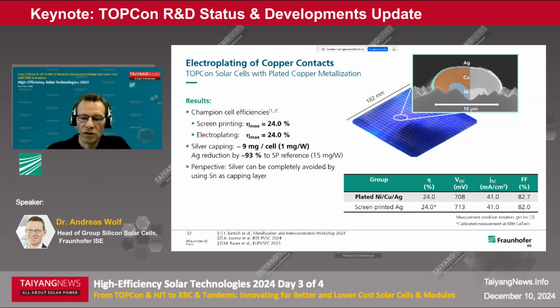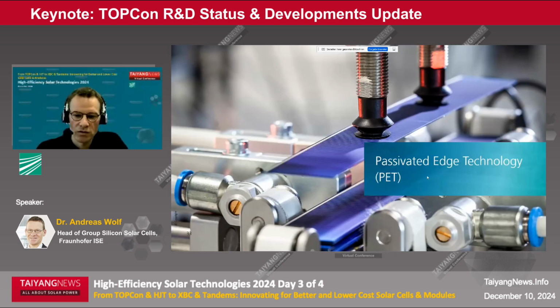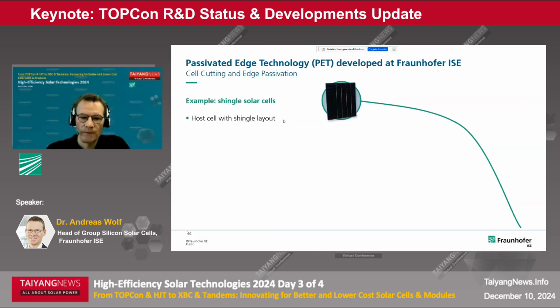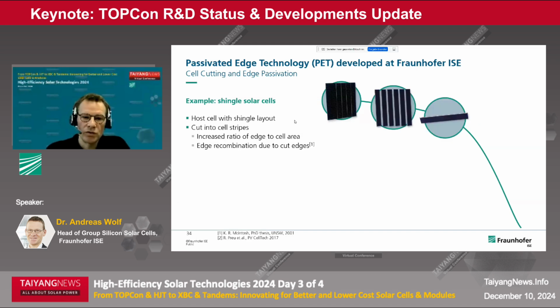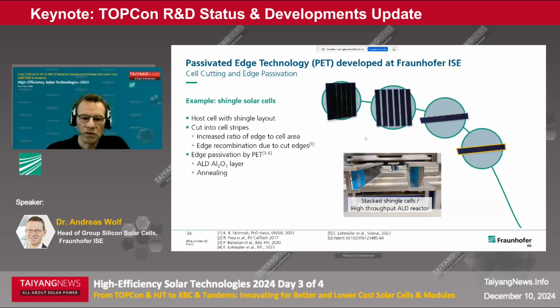Another technology that I'd like to draw your attention to is the passivating edge technology, which was developed at Fraunhofer ISE. It's a very important technology for shingle cells, but also for half-cut cells, which are already mainstream. We know that if you cut cells into pieces, you introduce recombination at the edges, and the passivated edge technology that we developed allows to passivate these edges, as you see here.